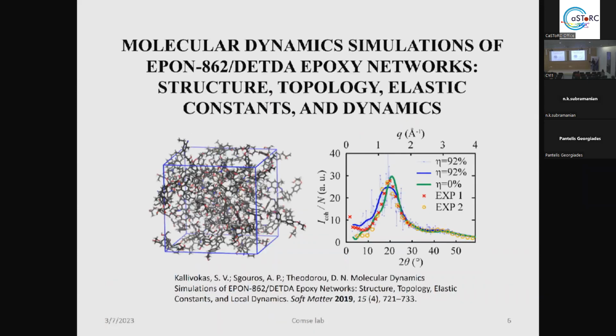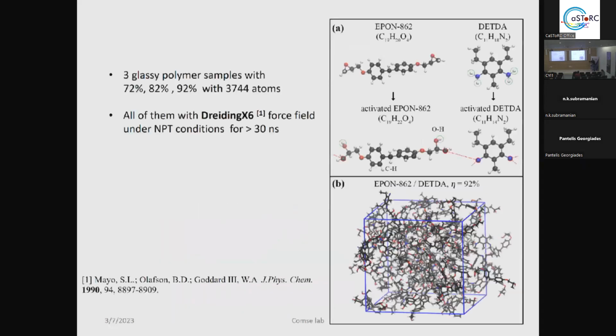Now, the first step of the research was to study a fully cross-linked network and to explore the topology, the elasticity, the dynamics, and the structure of this network. We made 3 different networks at 3 different cross-linking degrees, 72, 82, and 92 percent, with less than 4,000 atoms. We used the Dreiding exponential-6 force field, and under NPT conditions, we did equilibration for more than 30 nanoseconds. You can see the final image of the network here, for the cross-linking degree 92%, which is more or less a fully cross-linked network.